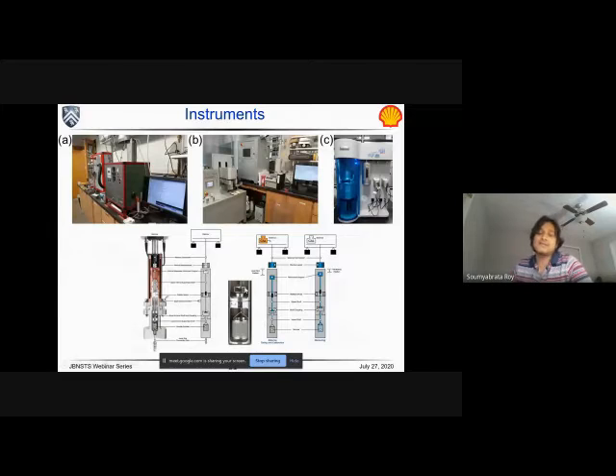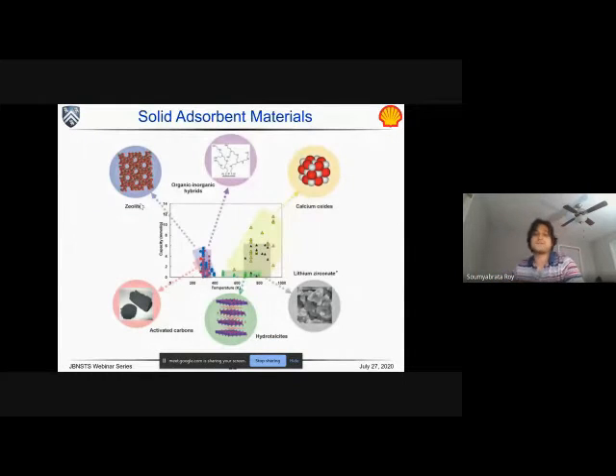One such balance is called a magnetically suspended balance, which is used in one of the instruments shown in B. It is called a Rubotherm instrument, and it has a magnetically suspended balance that you are seeing below. You put the material inside this jar, and once you put in some amount of CO2, if it is absorbed there will be a weight change, which you can measure as a function of temperature or pressure. The left-hand and right-hand images are volumetric methods where you can regulate temperature and pressure, and as I told you, they measure CO2 capture by Sievert's process.